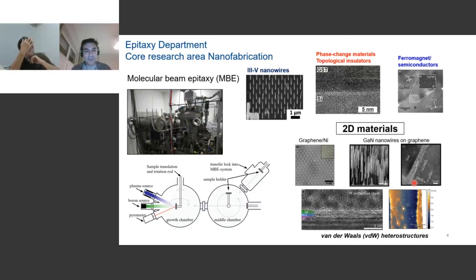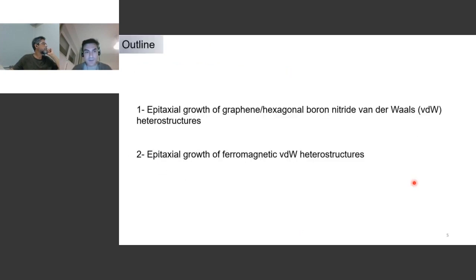And the main thing with MBE, as I already mentioned, is that you can grow at UHV conditions, ultra high vacuum, and this allows you to have very clean and very sharp interfaces. So MBE is a very powerful tool if you want to start with a new material, and if you want to really try to get the best out of a material or heterostructure, where you can really guarantee a very clean environment. And also the fact that you have UHV means you have proper conditions for in situ analysis, right? Like I mentioned, you could do some spectroscopy while growing, or, as I will show, some electron diffraction, so-called RHEED. So this is always very good to have in order to perform fundamental growth studies.